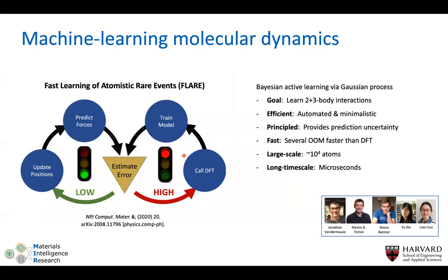So we have decided to utilize molecular dynamics simulation to study this dynamical phenomenon. In MD simulation, we move atoms in real time, and to do so, we need force fields or interatomic potentials. Empirical force fields tend not to be so accurate unless they are designed specifically for surfaces. And so what we decided to do is train a machine learning model that can learn and predict atomic forces just from atomic configuration, focusing on two- and three-body interactions.